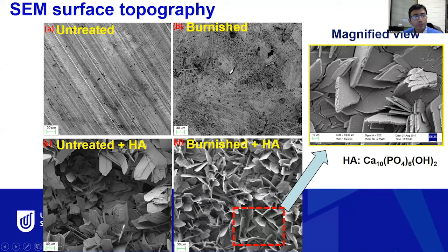But we can see a little bit of damage or delamination in some places of the HA coating when we deposit onto the untreated, I mean, without burnishing. And in some of the magnified views of the HA coating, we can see a very flower-like crystal structure, and those crystals would be around 10 to 50 microns in size, and as you can see, the thicker plates are around 5 microns in thickness.